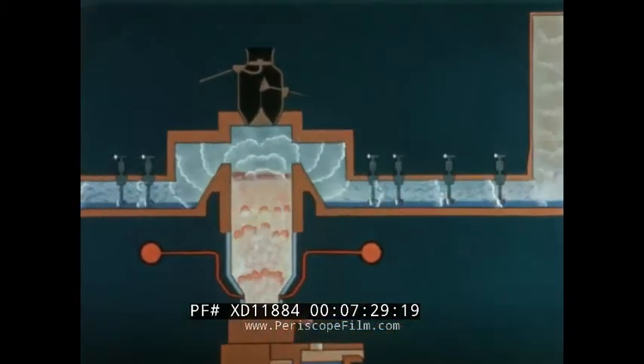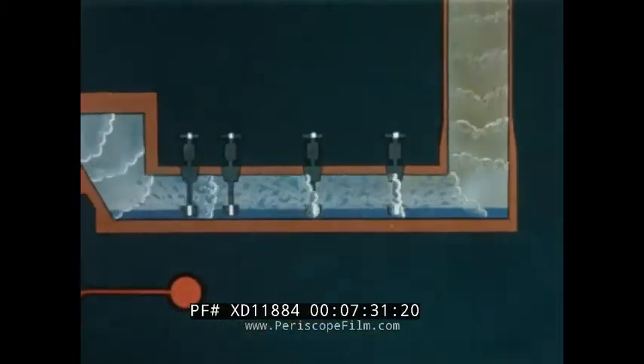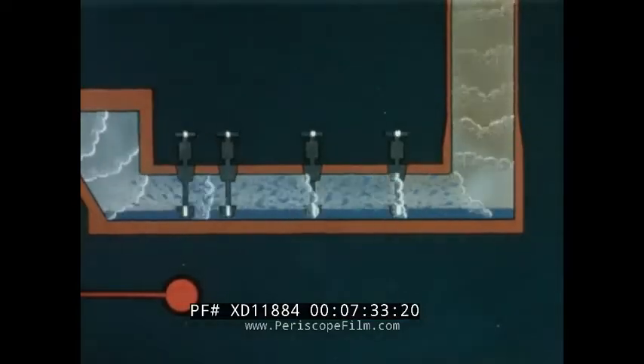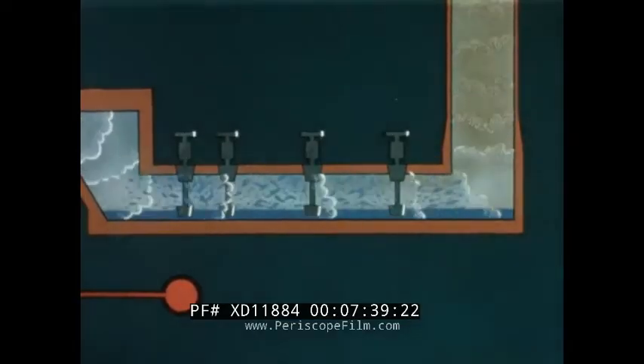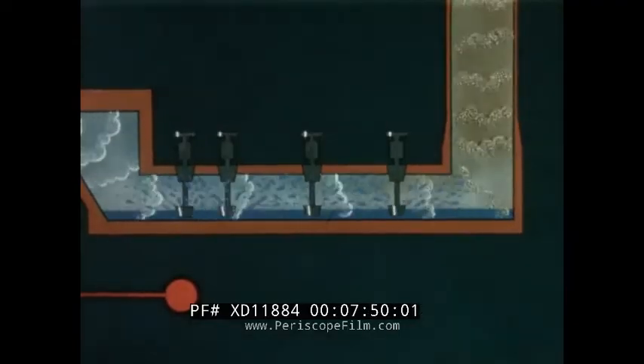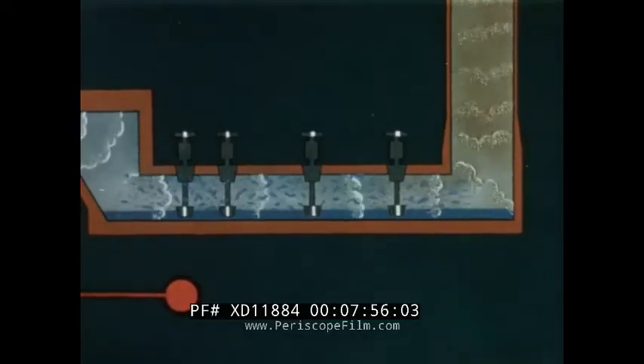Furnace gases and zinc vapor then pass into what is probably the most interesting feature of the process, the lead splash condenser. This condenser consists of a bath of molten lead into which rotors are immersed. These rotors produce an intense rain of lead droplets within the condenser. The zinc vapor passing through the condenser is shock-cooled by the lead droplets from 1,000 degrees centigrade down to 450 degrees centigrade, and is at the same time dissolved in the molten lead.